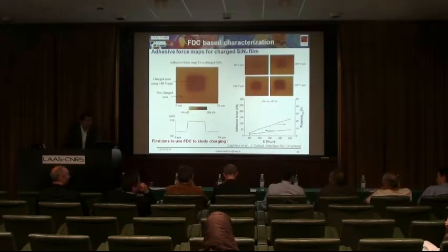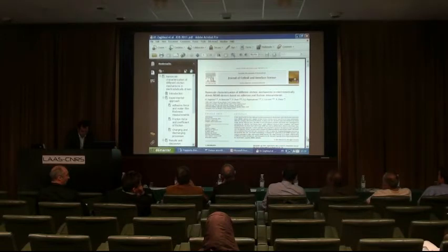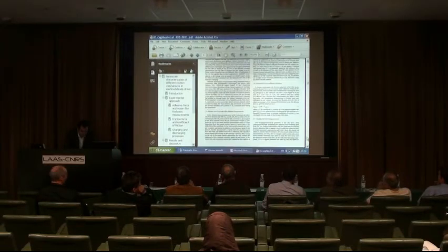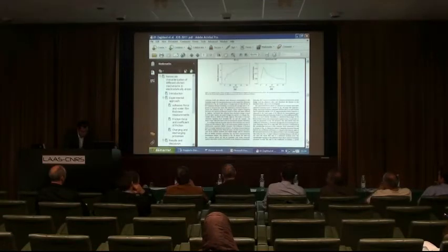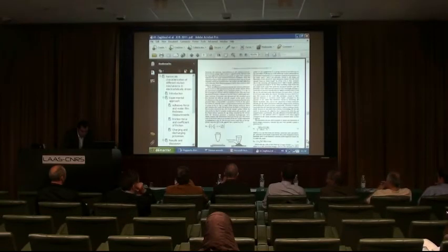While he's researching, we obviously have calculated contact pressure in AFM measurements, and the pressure is extremely high, on the order of hundreds of megapascals. The reason is we're using very short tips. So regardless of the mechanical properties, the contact area is very small, and the pressure is going to be on the order of 100 megapascals in typical silicon contacts. So we're dealing with very high pressures, although the loads are very small because of the short tip.